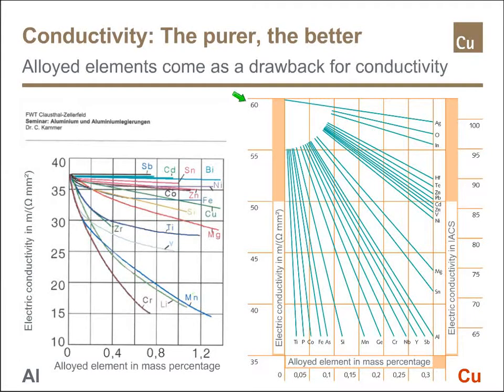Note that we have here 60 megasiemens per meter, and that is 35. And this scale also doesn't match that one here. So this scale for the aluminium is wider, and you see that the impurities are by far not that crucial and that dramatic with aluminium, but with copper, the purity is the criterion out of all that for the electrical conductivity.